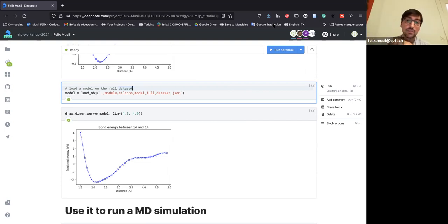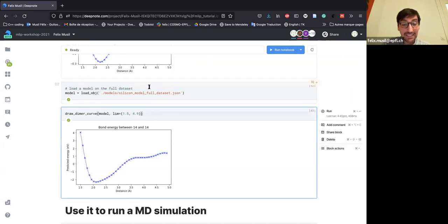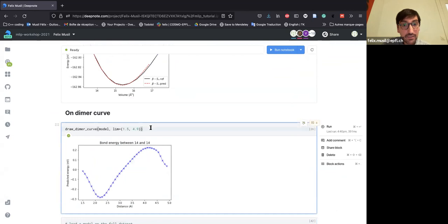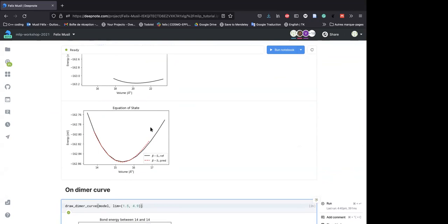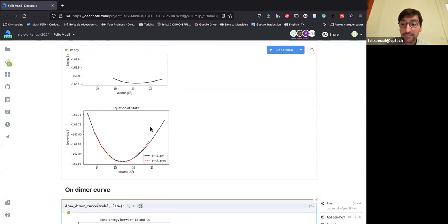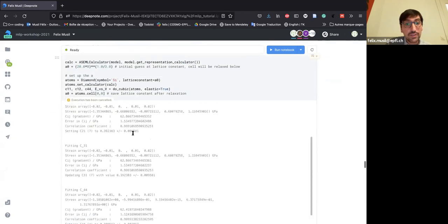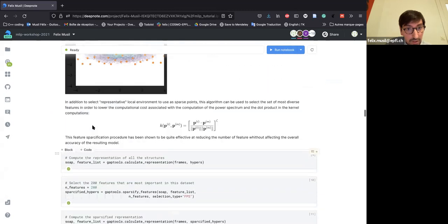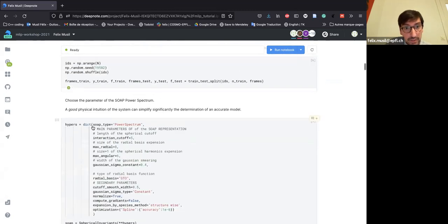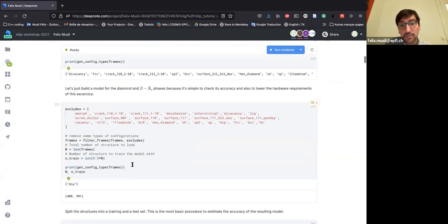So I think your question depends a lot on what you mean by good. As I tried to highlight in this tutorial, if you have, let's say, reference just for the diamond phase of silicon, for which there are also very good force fields, actually, then if you just want to have this phase right, you might also just use references from that, and you can see we already have a decent, a very decent potential using 400 references, 400 data points.